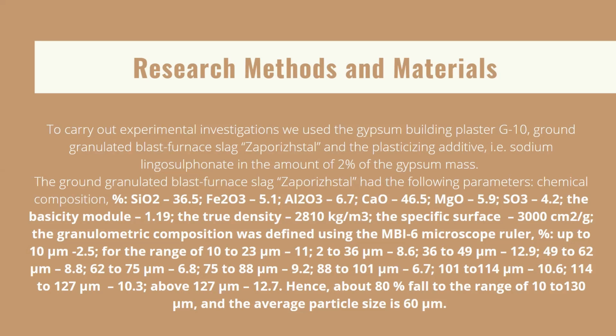The humidity strain was defined using prism-like specimens with a size of 160/40 millimeters that were cured for at least 7 days and nights and dried in the temperature range of 18 to 22 degrees and the relative humidity of 40 to 60% to get the constant weight. At least three specimens were used to test each composition. The specimen length L was measured in advance.